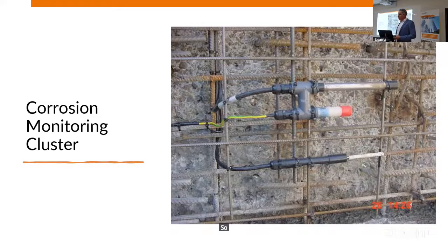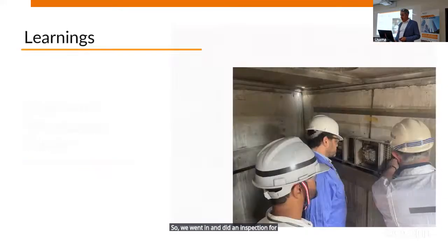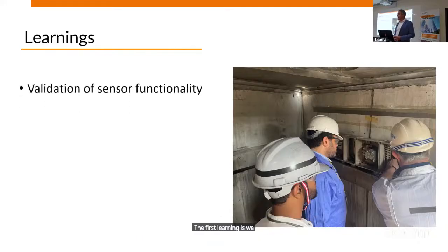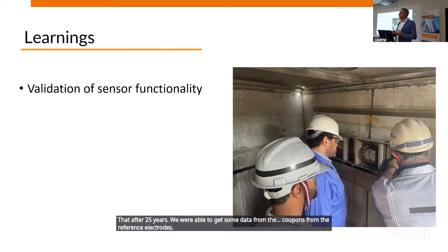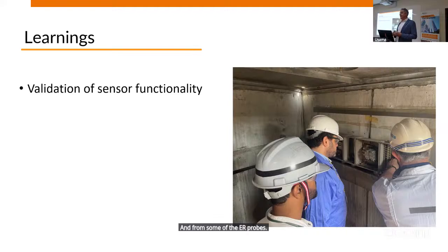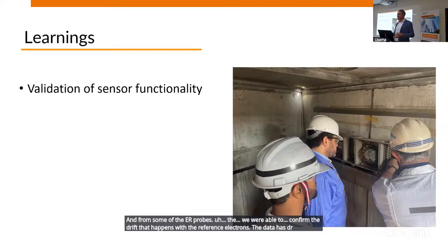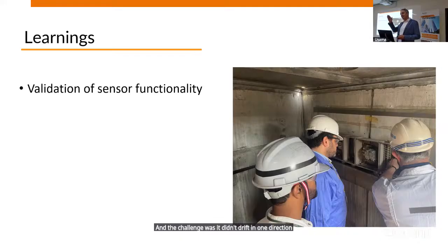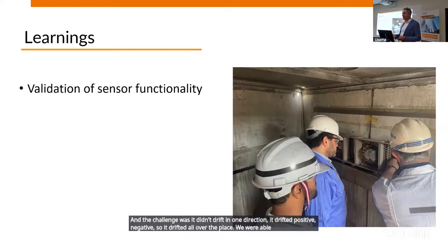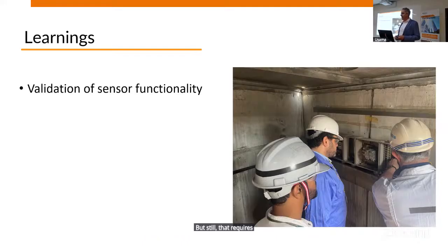So we went in and did an inspection for this structure, an inspection for the system. And we had multiple learnings from this exercise. The first learning is we validated the sensor functionality, that after 25 years, we were able to get some data from the coupons, from the reference electrodes, and from some of the ER probes. We were able to confirm the drift that happens with the reference electrodes. The data has drifted all over the place. And the challenge was it didn't drift in one direction. It drifted positive, negative. So it drifted all over the place. We were able to recalibrate, but still that requires continuous recalibration.